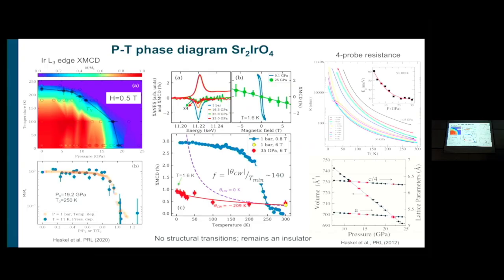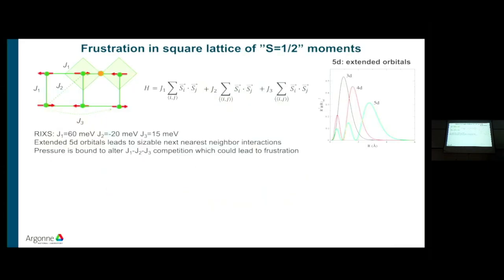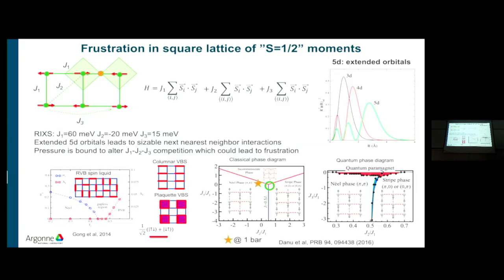If you do diffraction, you see no changes, no discontinuities in lattice parameters, no structural phase transition. So it looks like an order-disorder transition that may be something spin liquid-like. So how do you get magnetic frustration in a square lattice? Because you're looking at 5D orbitals, which are very extended. The spatial extent of these wave functions is very large. You may have higher order exchange couplings that may lead to frustration, and there are thousands and thousands of papers of how do you get a spin liquid in a square lattice.